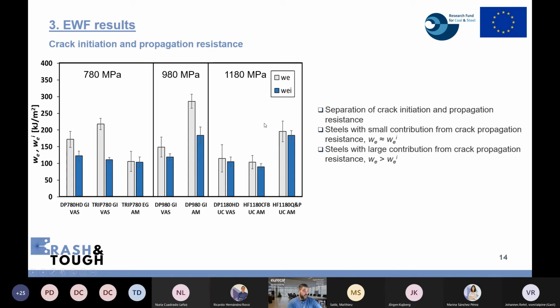One of the first things that we can see here are represented the values of the specific essential work of fracture, which are the gray bars, I'm sorry, and on the other hand, the crack initiation resistance values in blue. The first thing that we can see is that some materials show a small contribution from the total crack propagation resistance after the initiation, because you can see that the initiation and the full energy for propagation is quite similar.